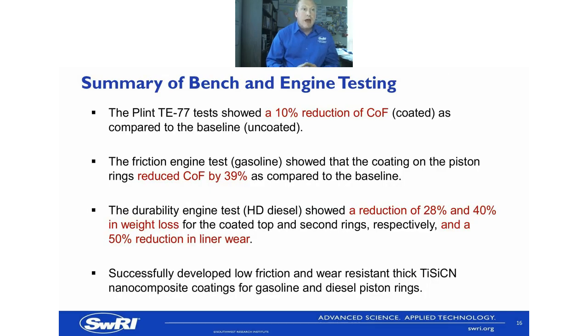The summary of that, when it came to an end, basically said that we'd shown a 10% reduction in COF in the reciprocating rig, a 39% reduction on average in the gasoline engine. We had a reduction of 28% and 40% in weight loss for the coated top and second rings in the diesel engine, and a 50% reduction in liner wear, which obviously shows that we've managed to develop very successfully some sort of piston ring coating.